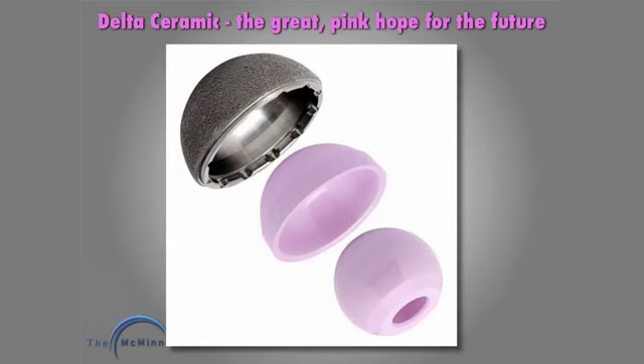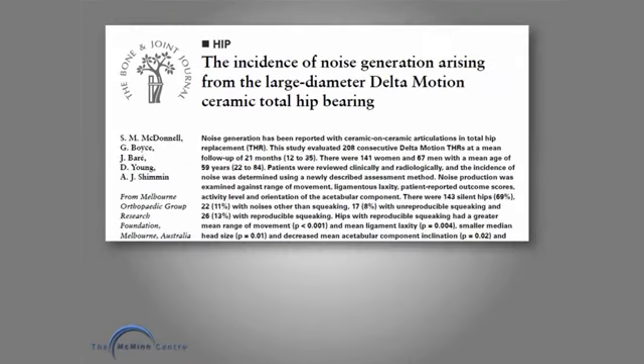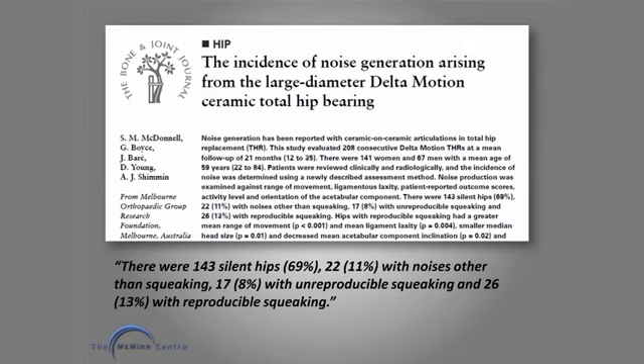However, they can squeak, particularly when there's a large-headed diameter Delta, like the Delta Motion. And this is a publication in the Bone and Joint Journal from Melbourne, Australia. There were 143 silent hips having had a Delta Motion device. That means there were 31% of the group making a noise, 11% with noises other than squeaking, 8% with unreproducible squeaking, and 13% with reproducible squeaking. That's a lot of noise, and noise in a ceramic is almost certainly an indication that the fluid lubrication layer has disappeared and you're getting direct ceramic contact.